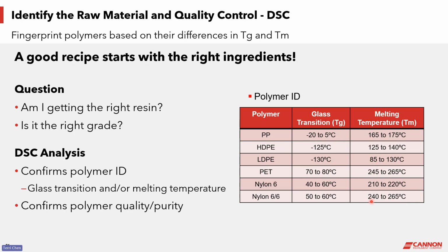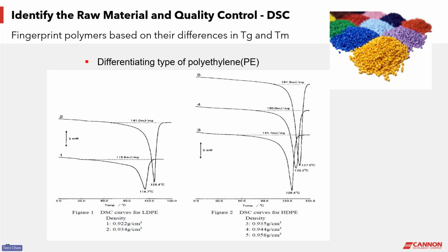Even within the same type of polymer, for example, polyethylene, the DSC measurement can also sensitively differentiate the differences in different grades. Here is an example of using DSC to differentiate the different grades of polyethylene resins. LDPE, low-density polyethylene, mostly contains long-chain branching structure. Therefore, they usually have relatively lower density. Figure 1 shows two different grades of LDPE resin with different density.